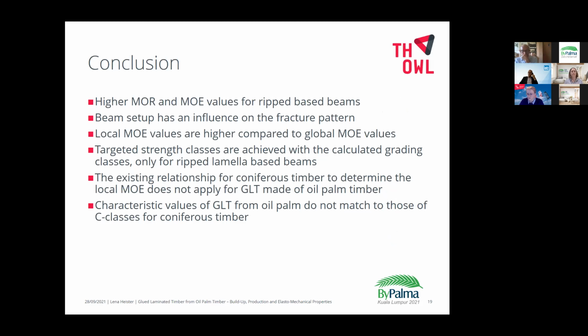Now I come finally to the conclusion. By grading the boards according to the density distribution across the cross-section of the board, the bending properties can be optimized compared to the conventional method of lamella production. Furthermore, the beam design, or the quality of the lamella and the beam structure, has an influence on the failure pattern. The procedure for calculating a particular strength class is generally correct. Both classes were achieved with ripped lamella-based beams. The existing characteristic values for the classification of softwood do not apply for GLT made of oil palm timber.